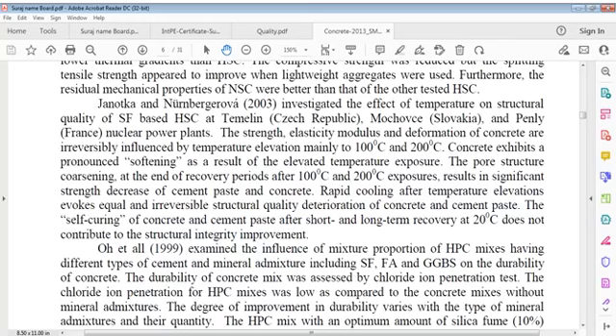Self-curing of concrete and cement paste after short and long-term recovery at 20 degrees Celsius does not contribute to structural integrity improvement. It's a very, very important research point. It says strength, elasticity modulus and deformation of concrete are irreversibly influenced by temperature elevation, mainly to 100 degrees Celsius and 200 degrees Celsius.